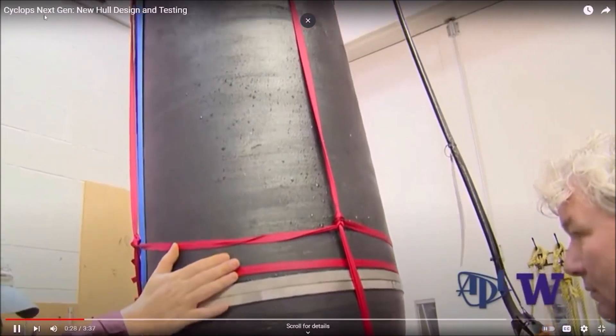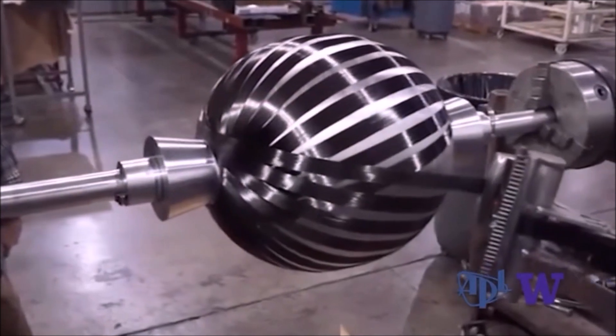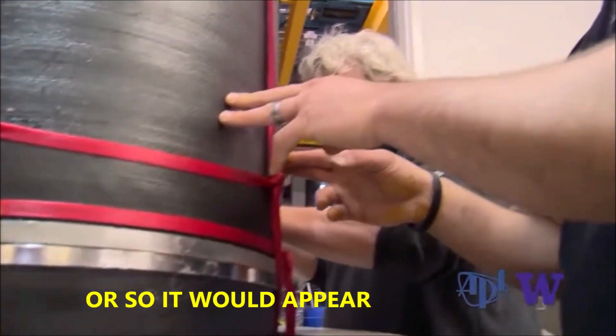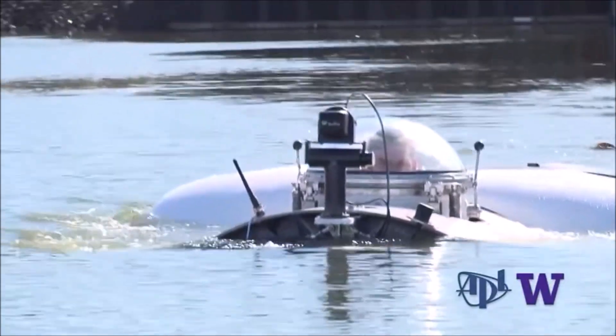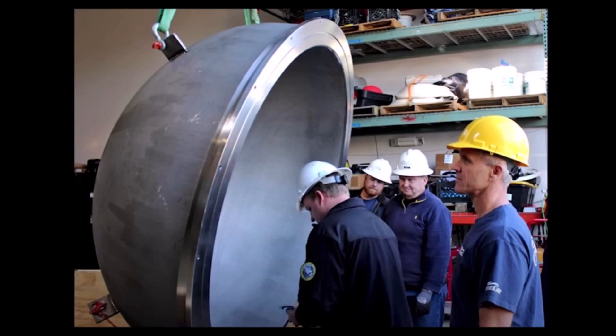As I've been doing further research, I've dug up some interesting information. Around 2016, Spencer Composites seems to have been the ones pushing the idea of using carbon fiber domes for the original design intent of the sub. Originally, Stockton wanted to have the entire thing made out of carbon. But Rush found in his one-third scale testing of hulls at APL UW that the carbon fiber domes just couldn't handle the pressure, and any kind of opening in them would cause a failure. So that's when the decision was made to go with three-and-a-quarter-inch thick titanium domes instead.